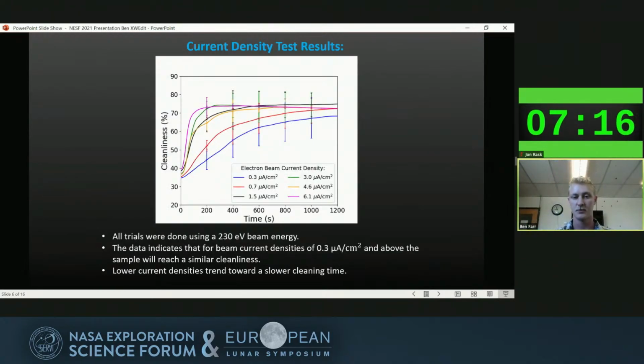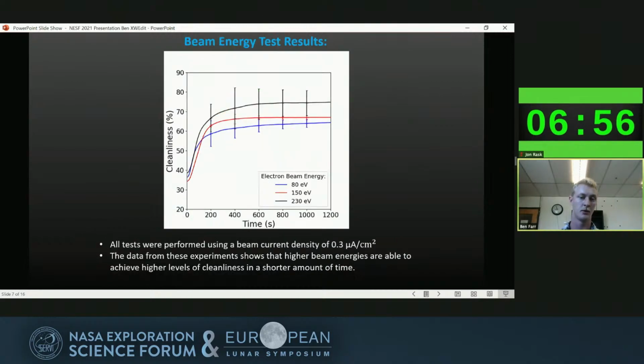For the first test, we wanted to see the current density and how that affected the cleanliness. We found that for anything above about 0.3 microamps per centimeter squared, we get the same final cleanliness. The only difference is the cleaning time. So for all the tests after that, we ran about 1.5 microamps per centimeter squared. We also tested the beam energy. We tested 80 electron volts, 150 electron volts, and 230 electron volts. And we found that it actually does get a little bit cleaner every time we increase the voltage.